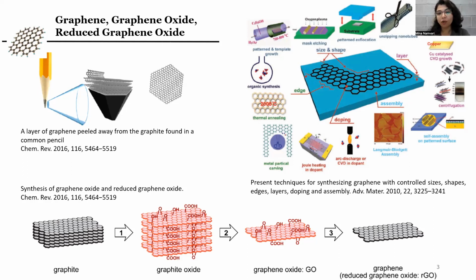So here is where graphene oxide comes into play. At the bottom of the screen, you can see the different steps to prepare graphene oxide and reduced graphene oxide. I will refer to graphene oxide as GO from now on. The obvious difference between GO and graphene is the oxygen functionalities on the surface and the edges. If we go further for the reduction, reduced graphene oxide is obtained. It is similar to graphene, but it's not as good because pi-pi stacking results in the agglomeration and stacking of graphene sheets, which diminishes its intrinsic surface properties. But to prevent this aggregation and restacking, modification plays an important role.